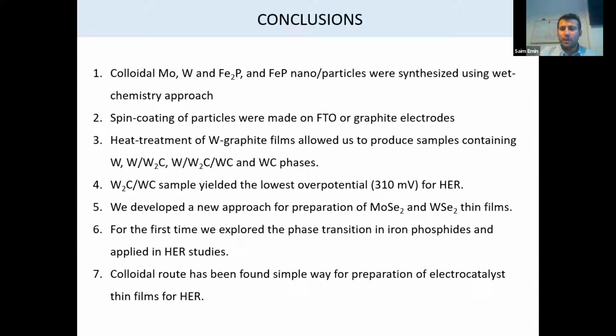Heat treatment of tungsten graphite films allowed us to produce samples containing tungsten carbides with different phases. And we found that one of the tungsten carbides mixed phase gives the lowest overpotential, around 310 millivolt for HER, for hydrogen evolution. We developed a new approach for the preparation of molybdenum selenide and tungsten selenide films.